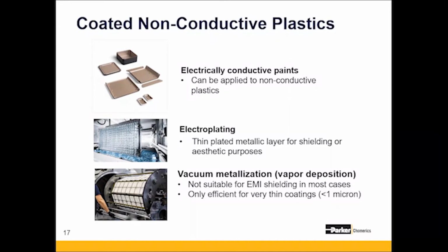The next category is electroplating, which is used to apply a very thin metal layer, and it can provide moderate shielding performance and some aesthetic properties. And finally, we've got vacuum metallization. It's another method of coating non-conductive plastics, but it's not necessarily suitable for EMI shielding. A lot of the time vacuum metallization is used for decorative work or mirroring. And really the reason it's not used for EMI shielding is because it's a very, very thin coating, less than 1 micron thick.